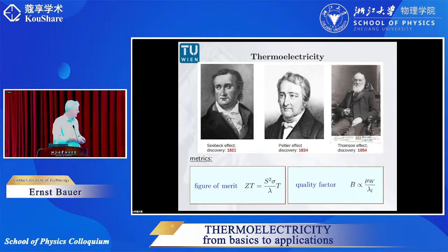We have a second metric, and this is called the quality factor. You can see here on the left side the figure of merit. It is a property which depends on quantities which we can measure, while on the right side there are more quantities which are direct materials properties, like the mobility of the charge carrier. So one can see the mobility of the material is a very basic quantity which helps to discriminate whether a material is a good thermoelectric material or not. That means materials having a high mobility are considered as good thermoelectric materials, or they turn out to be good thermoelectric materials, and the opposite is true as well.